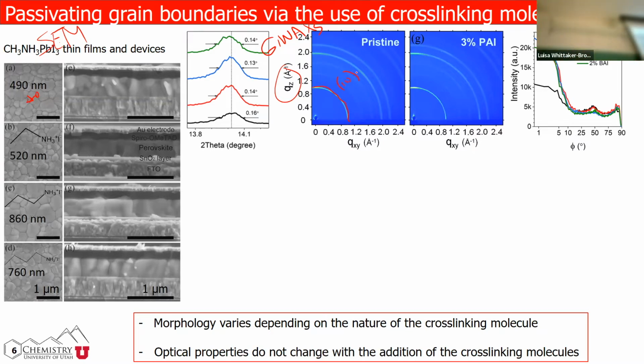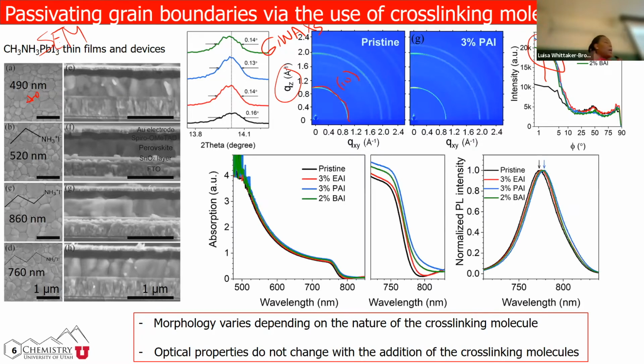So if we azimuthally integrate all the intensities around that, then we can say which one is more crystalline, okay? You could just look at it and ask which one is brighter, and you can probably play that game, but I don't think it will get published if we actually do that. So we azimuthally integrate, and then we see that whenever we put in the alkyl ammonium cations, we gain intensity, which is an indication that the crystallinity is increasing when we put in these alkyl ammonium cations. All right, so how about optical properties?